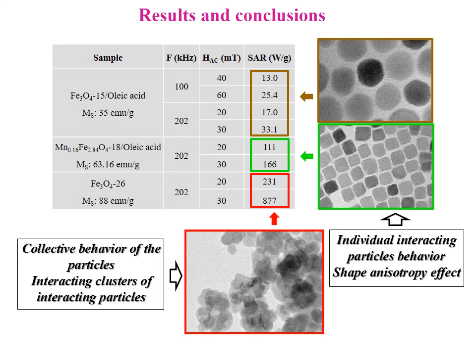The heating capacity of nanoparticles in the present alternating field has been evaluated from the magnetic hyperthermia measurements using the calorimetric method. The amount of heat generated by the magnetic particles has been quantified by the SAR values obtained from the heating curve using the initial slope method. The measurements were made with the particles suspended in water at different frequencies and magnetic fields.